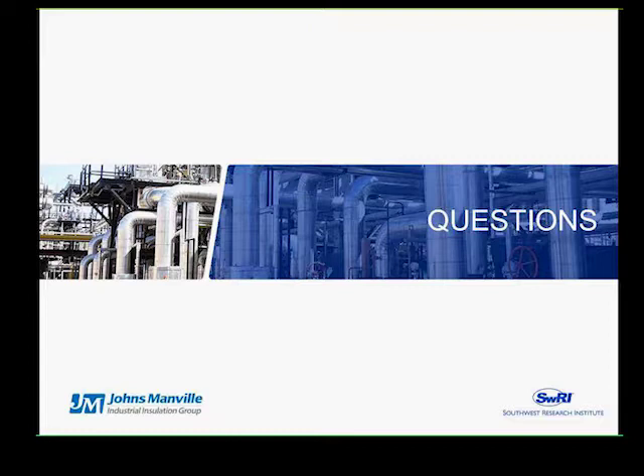Great. So Leo, what is the effect of pH on corrosion? pH, as it relates to the environmental conditions around the pipe, will have a significant effect on the corrosion rate of bare metal, and in some cases, to some extent, to coating degradation. High pH in carbon steel may have a passivating effect, whereas high pH, greater than 9, on TSA may imply that the aluminum can corrode at much faster rate than if the pH is lower than 9. So certainly pH has an effect on the corrosion rate depending on which metal you are using, and of course the coating type that is being employed under insulation.